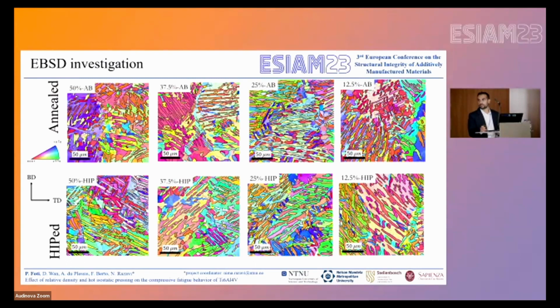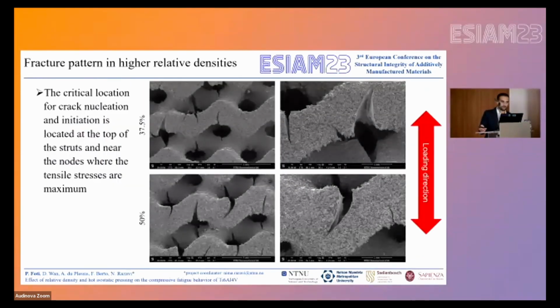Going through the microstructural investigation, as you can see here, there is no significant change in the morphology and the grain size of the annealed and the annealed and HIPed specimens. And these prove, of course, the results that we have seen in terms of fatigue tests.